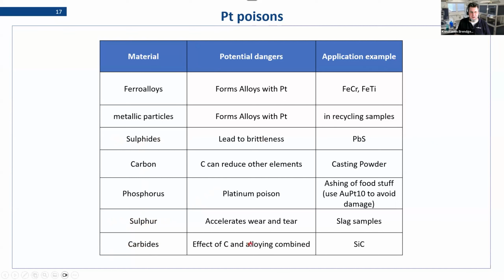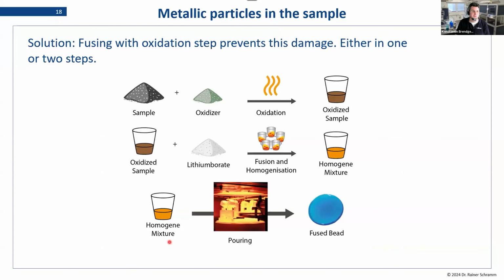Last but not least, carbides combine all these effects. If we're looking at silicon carbide, for example, you have the effect of the carbon being a reducing element, and at the same time we have metallic silicon that can directly damage your platinum. So you basically have the worst of all. Be very careful with carbide samples. They can be done. You just have to stick to a few rules.